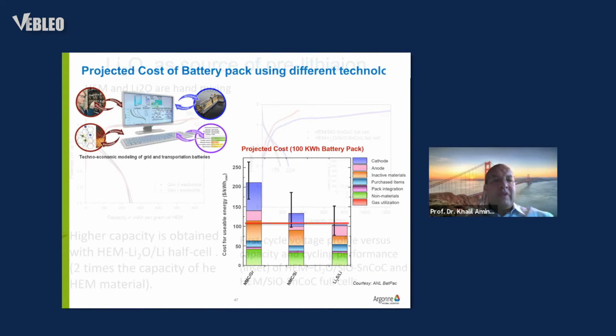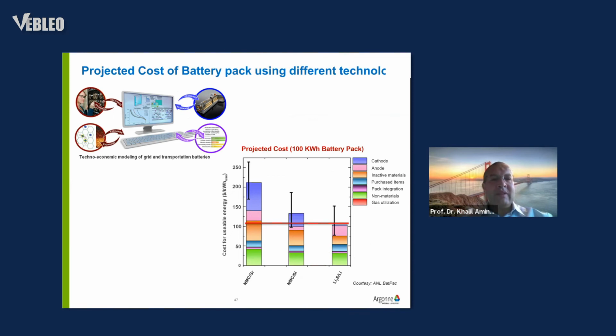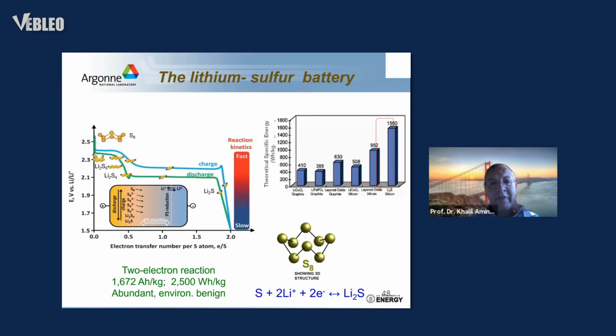Now, if you use the techno-economic model that Argonne developed and is available online for everybody to use, if we use the NMC graphite, we are at about 220. This is the cost, and its distribution. If we move to the silicon, without pre-lithiation, we are at 125. So we are in the near term, if you want. If you add the pre-lithiation, we drop to 100. However, if you do sulfur, you can see clearly that the cost drops significantly. And that's the reason why I would like to talk about sulfur in my last part.